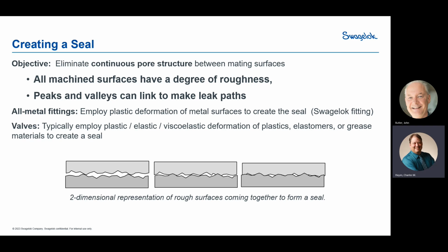So how do you deal with this when you're trying to make something like an all-metal fitting? You deploy plastic deformation. You move the materials in such a way that they will create a seal on those surfaces. The Swagelok tube fitting does this, and we'll show in a little while exactly how that works. The way you deal with it in valves and other products is usually to employ something else, a plastic or elastic rubber component, an elastomer, viscoelastic things, and they deform. Sometimes people use grease to form seals, and that's not a really great idea.